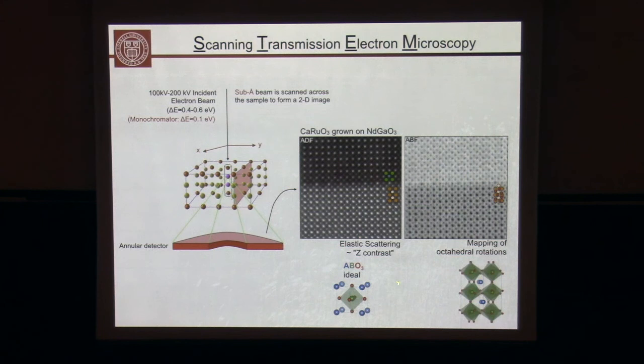Now, a lot of the physics, and I had a beautiful discussion this morning about octahedral rotation. And so ideally, if you want to understand how materials perform, you want to be able to identify the location of cations, but also of the oxygens in the sample. And so by going to low detector angles, this is what we call bright field imaging, we are not only sensitive to heavy cations, but also to the oxygen atoms in the sample, and we can extract rotations and tilts across an interface. So this is very powerful.